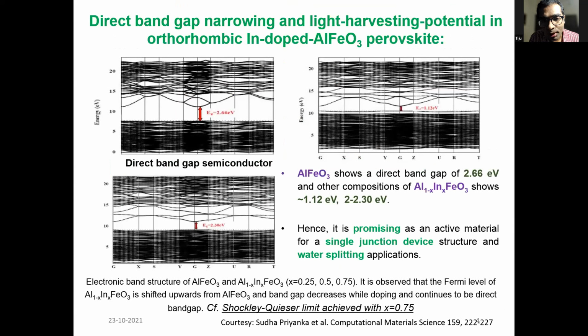So this is an example of a prediction that was made a few years ago. And primarily, the context of this prediction was that we were chasing materials that are direct band gap and which would ideally provide us with Shockley-Queisser efficiencies. What does that mean? It means that it would ideally have a direct band gap of roughly 1.1 electron volts. And the reason why it is particularly interesting is because you can demonstrate that at that band gap, you will be able to get maximum single junction photovoltaic efficiencies.